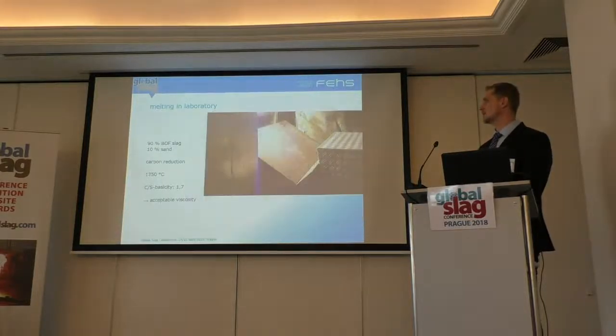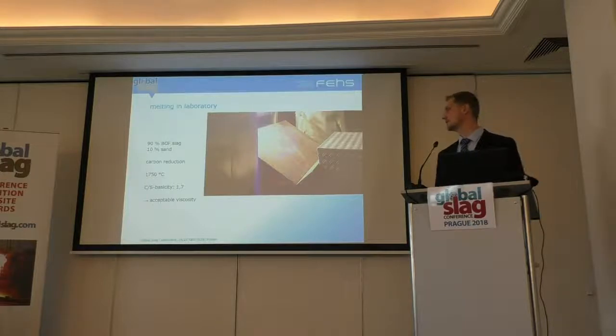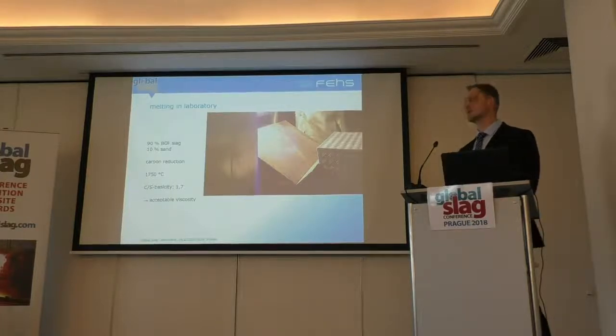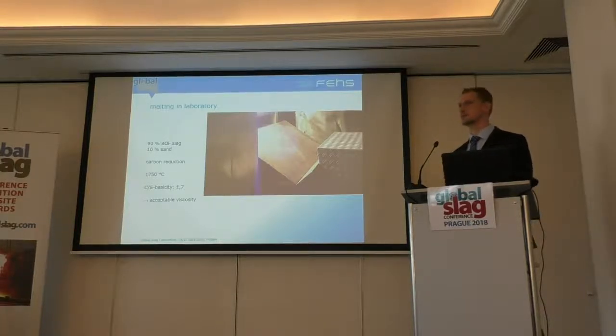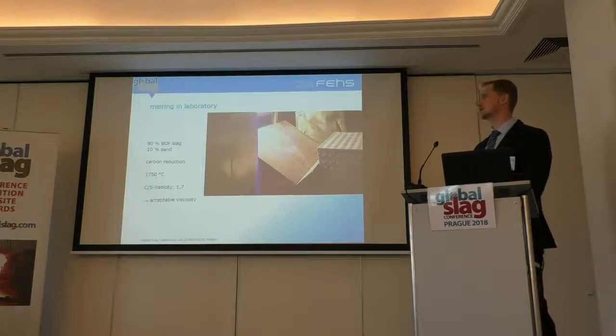The metal was not able to go down to the bottom, and we had more or less the same. Due to this, we made a further trial where we increase the temperature. So the same basicity like before, but now we increase the temperature to 1750 degrees. That's a little bit untypical, so we have a higher wear of refractory in operational practice.